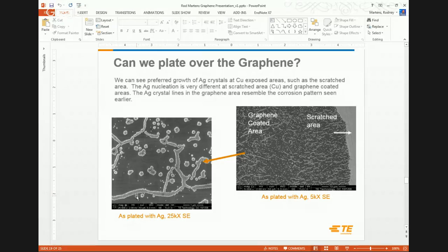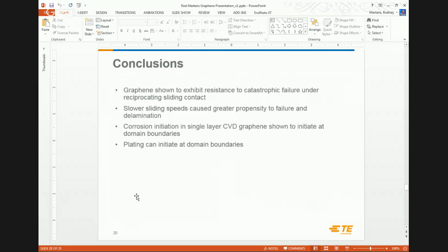So now what's interesting here is, I'm not convinced that graphene is durable enough to be on the top surface of an electrical contact. There's no way that it's going to be able to withstand the loads that we care about. However, can we exploit it by burying it and then plating on top of it? So now we have basically an integral diffusion barrier built into the contact interface. So that's really what we're looking at right now.